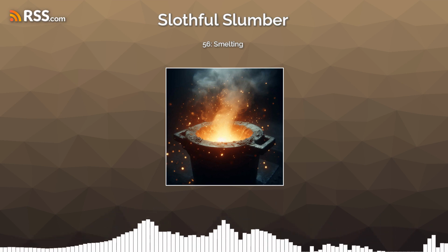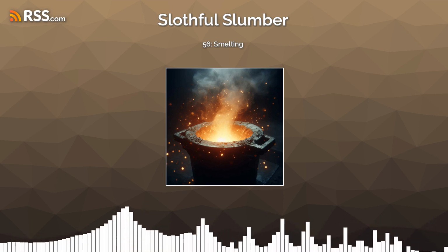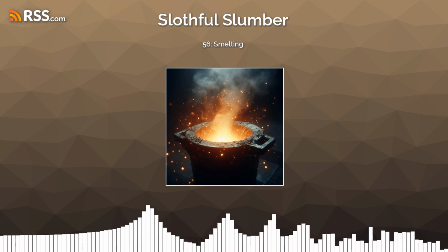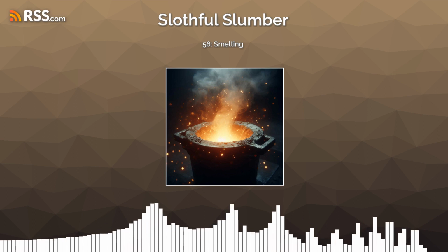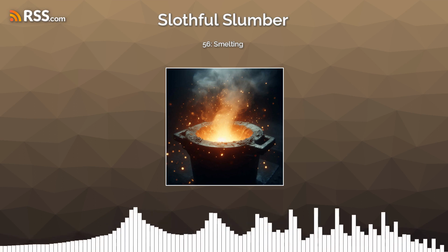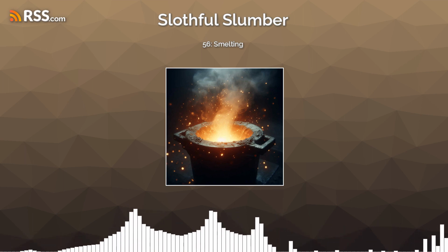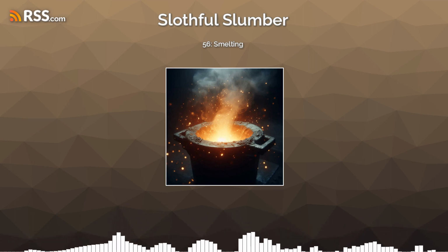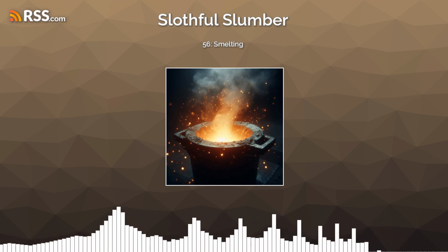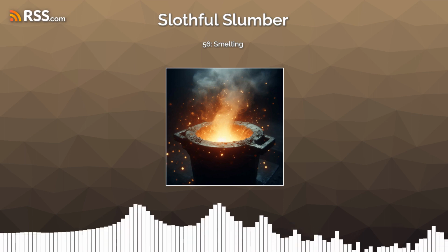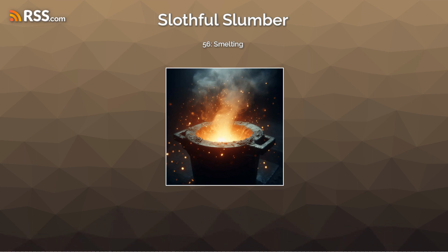The precise details of the process vary from one furnace to another depending on the mineralogy of the ore body. While reverberatory furnaces produced slags containing very little copper, they were relatively energy inefficient and off-gassed a low concentration of sulfur dioxide that was difficult to capture. A new generation of copper smelting technologies has supplanted them.